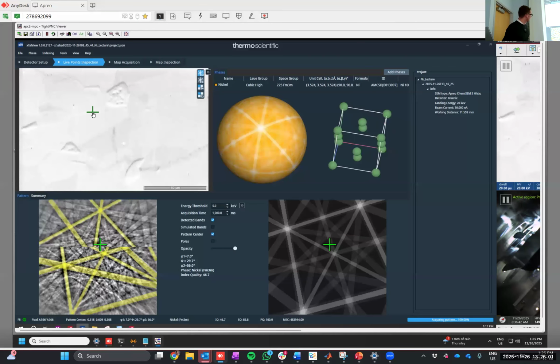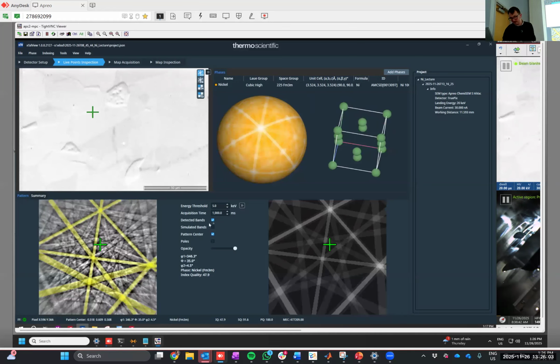Why do I hit near grain boundaries? There's a single diffraction pattern as presented, and the detected bands and the pattern center. So that's the pattern that's collected. This is on a direct electron detector. So this is using a Timepix 1 detector for this particular setup.